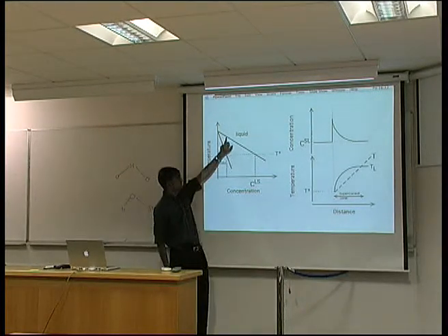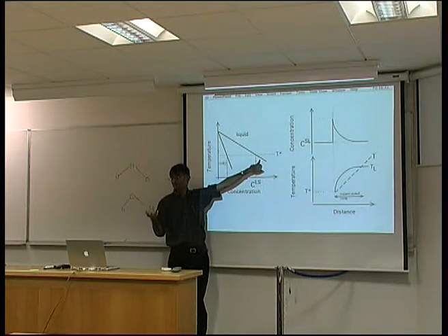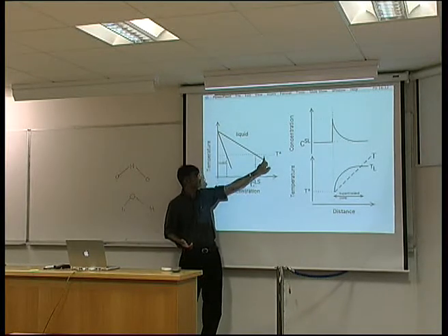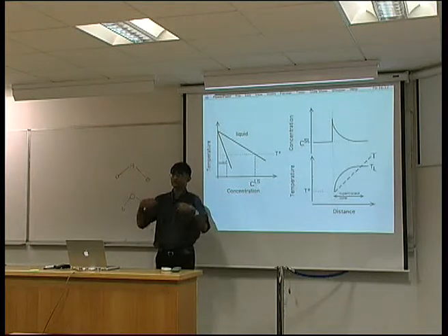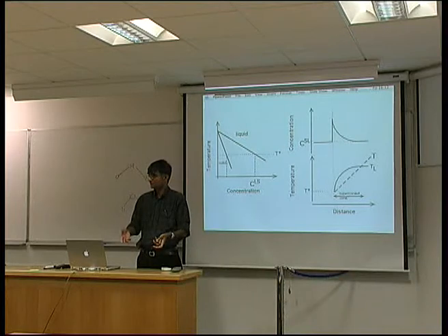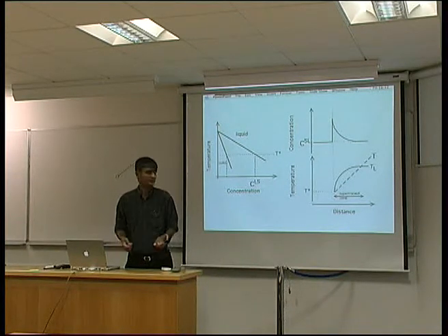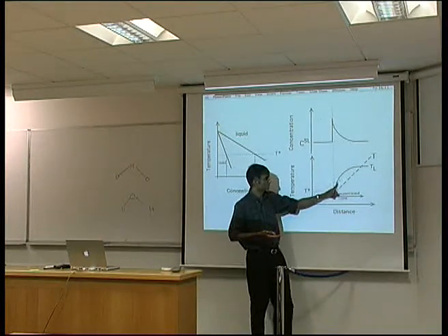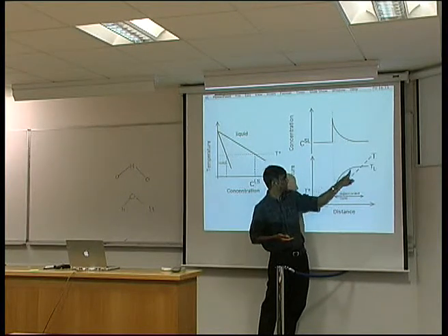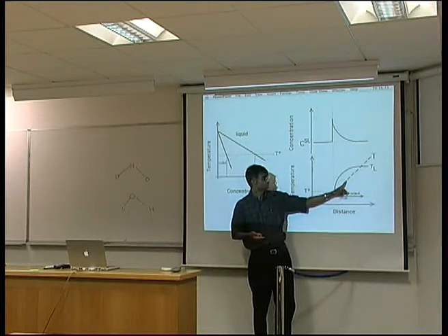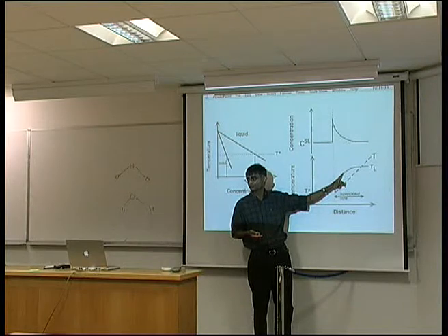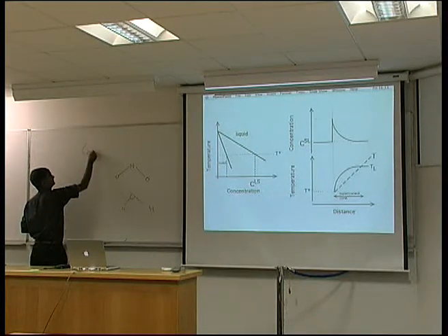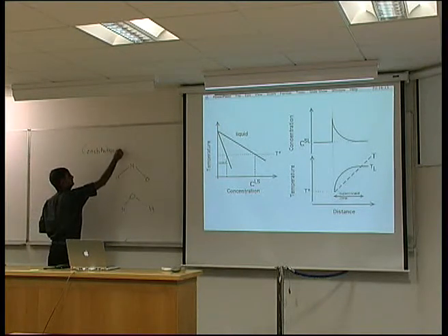But if you look at this phase diagram, the solidification temperature, which we call the liquidus temperature, means that if I have a liquid of this composition, it will start solidifying at this temperature. If my liquid is richer in solute, then it starts solidification at a lower temperature. That's the reason why when you put salt on roads, the ice melts, because the freezing temperature of salty water is lower than that of pure water. So in fact, the freezing temperature varies with the solute content. If I plot the freezing temperature now as a function of the solute concentration, then it follows a curve like this. So notice there is a region here where the actual temperature is below the freezing temperature. This is what we call a constitutionally supercooled zone.